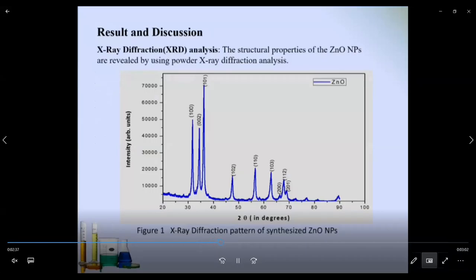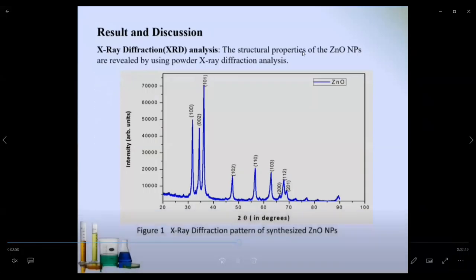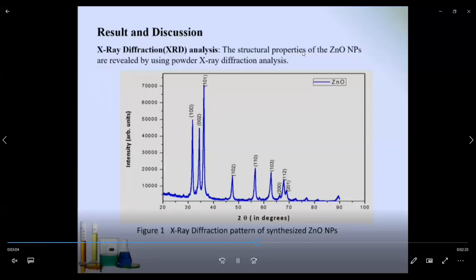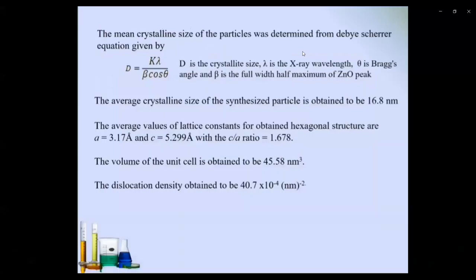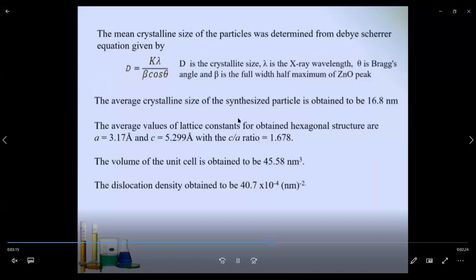Firstly, from the X-ray diffraction pattern, we can observe here that strong diffraction peaks are obtained at different diffraction angles corresponding to the peak index. And all the peaks are compared with JCPDS data and confirm that synthesized nanoparticles are in hexagonal structure here. The narrow and sharp peaks indicate the synthesized sample is well crystalline. And the high intensity peak at 101 confirms the formation of zinc oxide nanoparticles and indicates anisotropic growth with preferred orientation of the crystallites. And further, the mean crystalline size of the particle was determined from the Debye-Scherrer equation so that the average crystalline size of the synthesized particle is obtained.